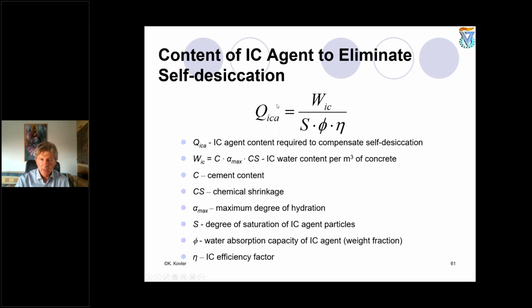How do we calculate the content of the IC agent, the internal curing agent? By a very simple formula. We need to know how much water is needed. This is not a part of the mixing water. It's extra water. We use IC as an index, internal curing water, per cubic meter of concrete, of course.